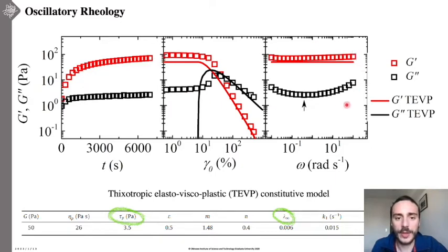And also in the frequency sweep we can observe that the material is mainly elastic. Indeed, G prime is greater than G double prime, and it shows a kind of fingerprint of a gel, where G prime and G double prime are pretty much independent from the angular frequency.